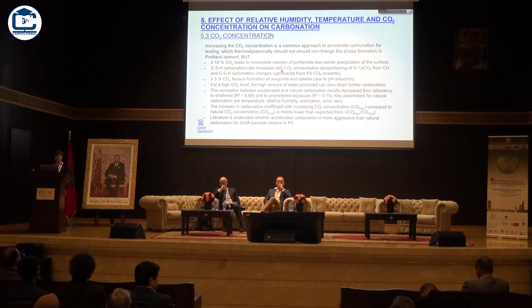For instance, more rapid CSH carbonation versus portlandite carbonation. Different polymorphs that are formed. Furthermore, carbonation is a reaction in which water is produced. So this means water production. It may mean saturation of the concrete pores, and hence a slowdown of the ingress of carbon dioxide in the material. So this might counteract the faster carbonation that you might normally expect at high carbon dioxide levels.